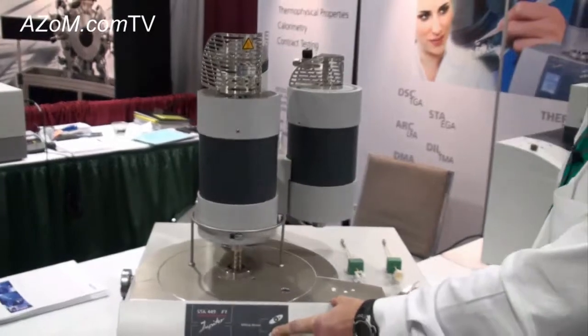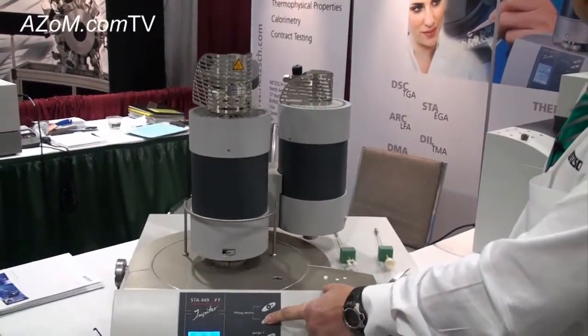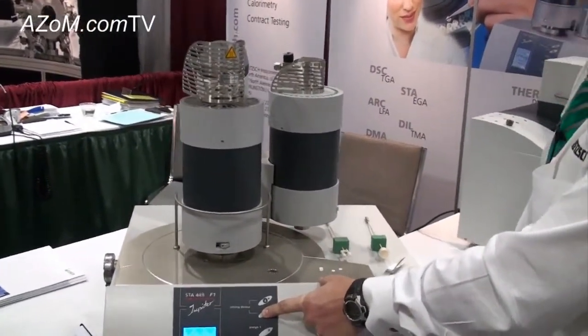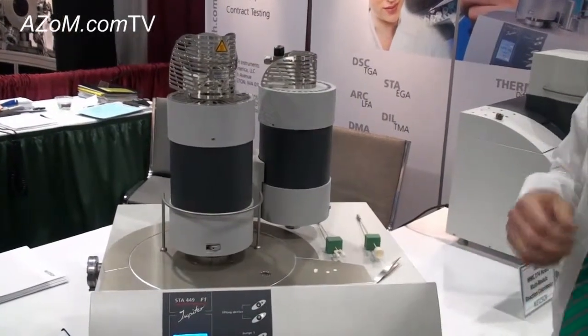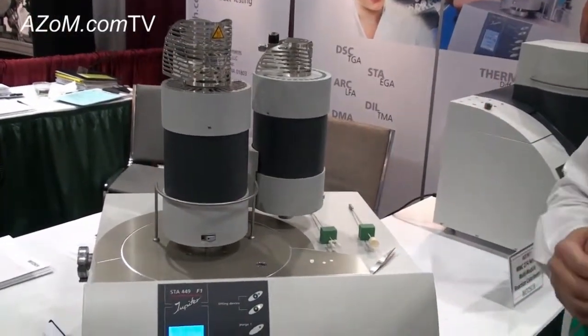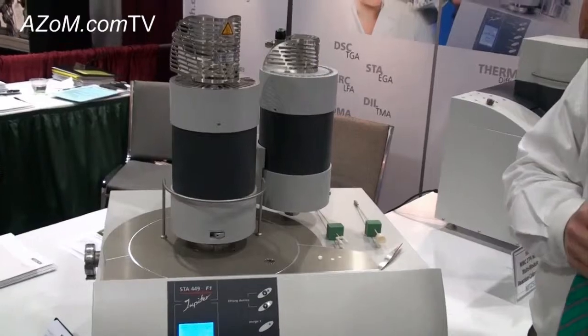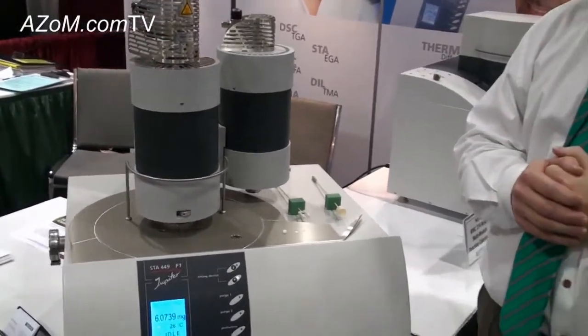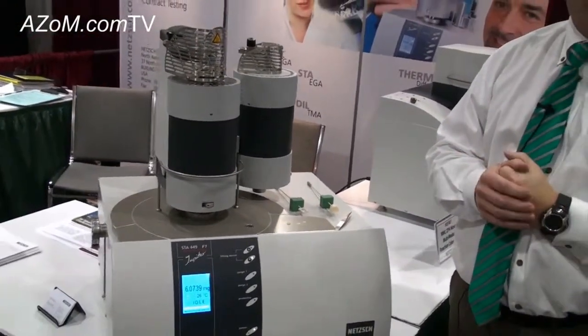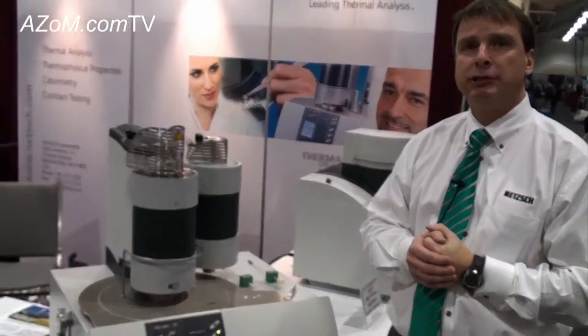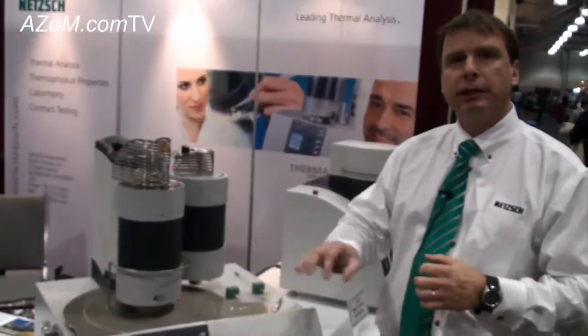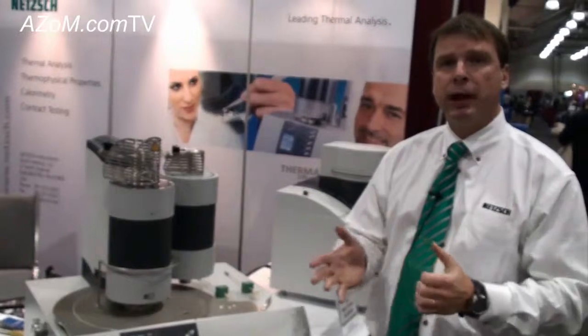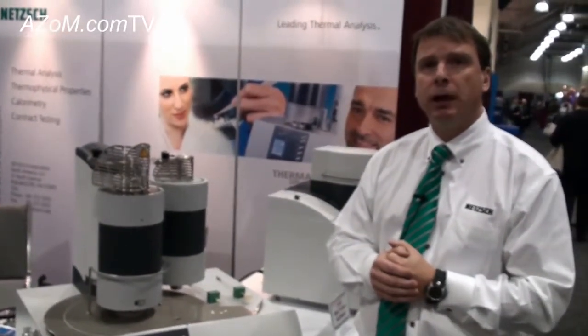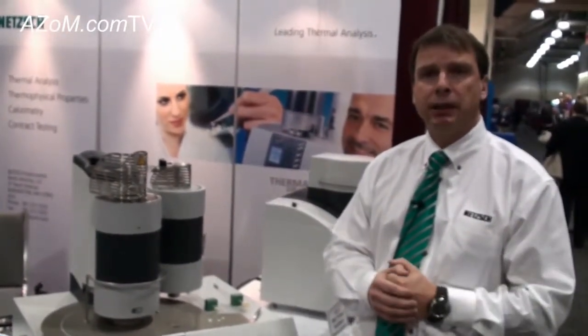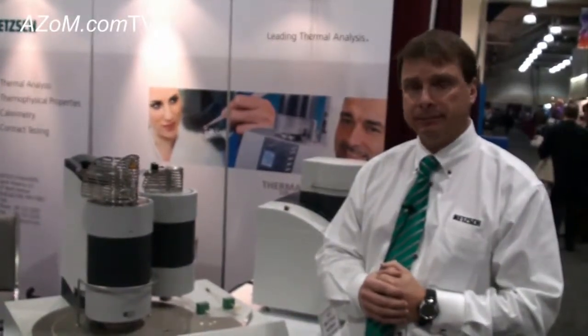And we typically will measure over a controlled temperature ramp, or also isothermal conditions, or a combination of ramps and holds. We use this to measure the properties of materials, such things as melting points, phase transitions, glass transition temperatures, and also, of course, the mass change as you get thermal decomposition as a function of temperature, or even if it's going to oxidize, you would actually see a mass gain.